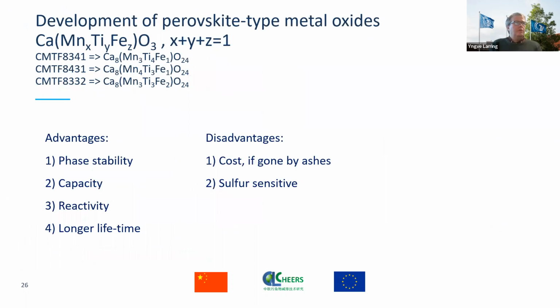When it comes to the perovskite, we made 3 different compositions. It's only different compositions of the manganese, titanium, and iron, in a 4-3 system. The advantage of the perovskite is that it can be tuned to a much higher degree to get higher stability, more or less capacity, and a little change in where it releases oxygen, if you want CLOU or CLC. We want something with high phase stability, because then we have a long lifetime, a decent capacity, not too high. We want relatively good reactivity, of course, and a longer lifetime than the other ones.